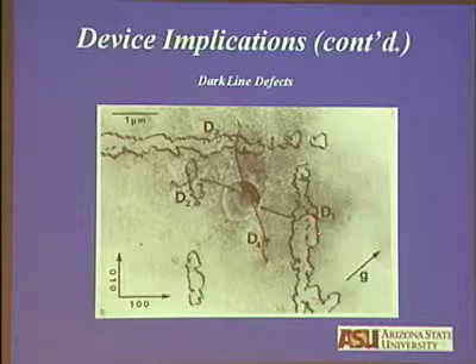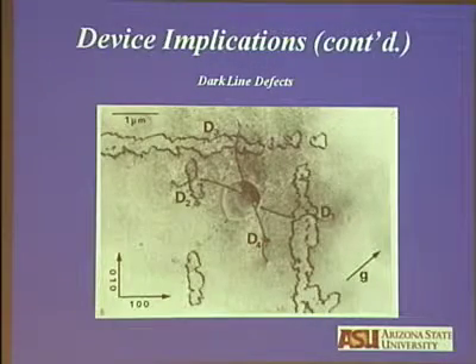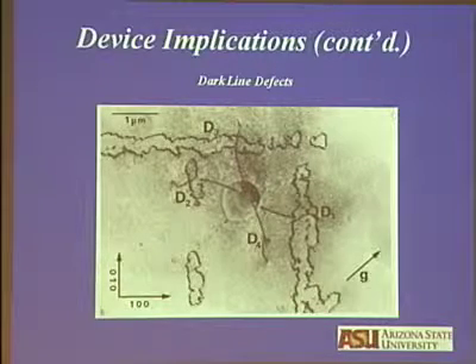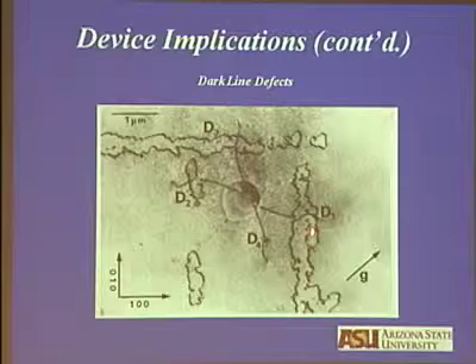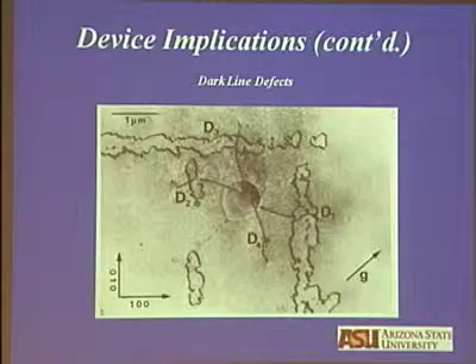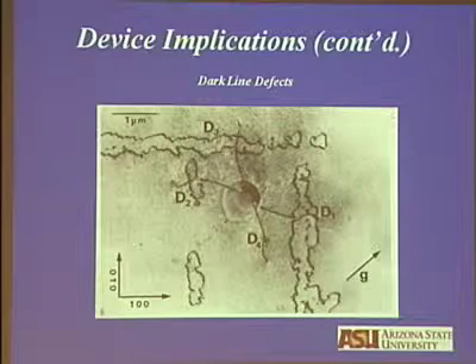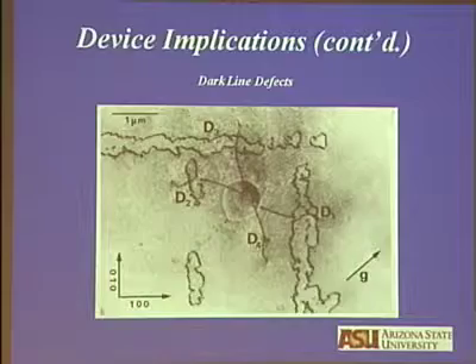And this is another dislocation multiplier. It already tells you if you want to make reliable lasers, you better reduce the dislocation density to a minimum in your material. Now the structure, these are the dipole structures. How do they evolve? And we had argued, and other people had argued, it's a tongue twister, what I'm going to say, non-radiative recombination enhanced glide and climb. When electron-hole pairs combine very close to the dislocation, it doesn't emit a light photon. Photons don't come out. But that energy gets coupled to the dislocation in the presence of stress, and the dislocations climb and glide.